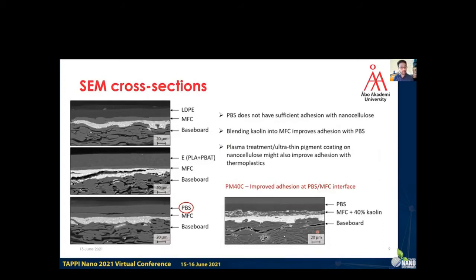So looking at SEM cross sections, here on the left, I have the cross sections for MFC containing multi-layer paperboard with LDPE, Ecovio, and PBS from top to bottom respectively. And one can see the various layers easily. So we have the baseboard, pigment coat, pigment surface, and MFC, and then LDPE, and here the other polymers respectively.